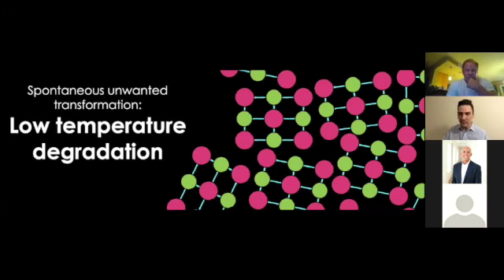So with zirconium, we got all these tetragonal crystals. Remember, if we introduce a crack to them, they transform and become less dense, and they become bigger, and they stop the crack from growing anymore. And that was called the transformation toughening. Well, sometimes, even though we don't want it to happen, they just will spontaneously transform and get bigger.